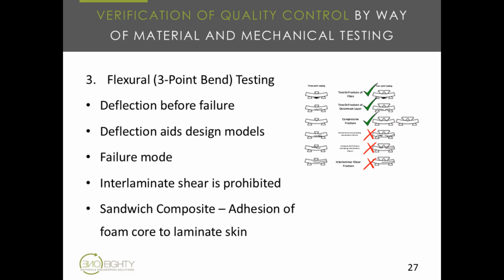Once again, you also want to determine what the failure mode is under flexural force, because interlaminate shear is strictly prohibited. Interlaminate shear would be when the cracking occurs in the composite but parallel to the fibers. And the reason why that is so detrimental is because there is no resistance to that crack forming if it starts in a parallel position. So once that crack forms, it will continue if it's not detected. So you could end up with an entire, I actually have done a case where the whole deck was delaminated and it's lost all the structural integrity just from a delamination crack.